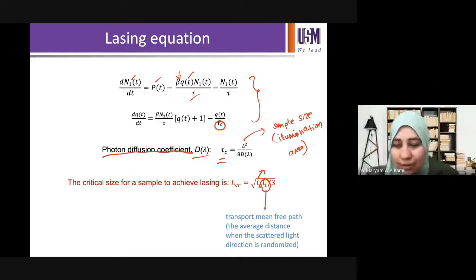Now, this is also dependent on, because we are depending on scattering. Remember, we are dealing with the change of refractive index. A lot of scattering happens. We want to achieve scattering that's inside and not going outside very quickly. So it depends on something called the scattering mean free path, which is actually, I would say, inversely proportional to the scattering cross section.